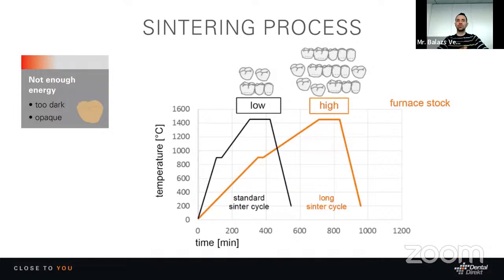This is the opposite. For example, in the first picture we saw that in case we have too much energy, we will have a brighter color. On the other hand, when we do not have enough energy during the sintering process, our crowns will be too opaque and too dark. It could be not just a problem of the sintering furnace, but of the wrong program that you chose. For example, if I fill our sintering furnace completely with crowns and bridges, of course we need more time to reach that temperature. So we always have to pay attention to choose the proper sintering process and sintering cycles.